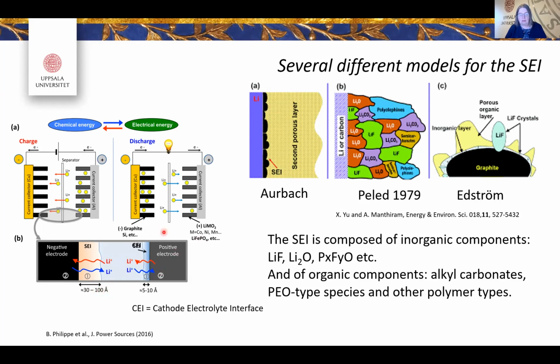If you go to the positive electrode, which is far from this reactive lithium potential, like even 4 volts, maybe even higher, you actually don't have this kind of SEI. You have instead what we call today a cathode electrolyte interface, which is more like corrosion products, HF formed, reacting here. So both the surface of the electrode as such can rearrange, but you have a much thinner and a little bit different composition of this.